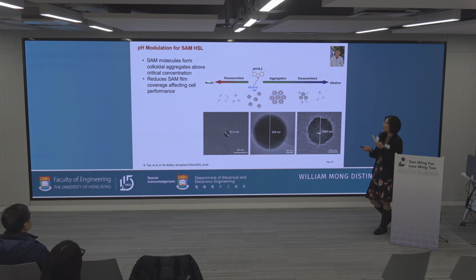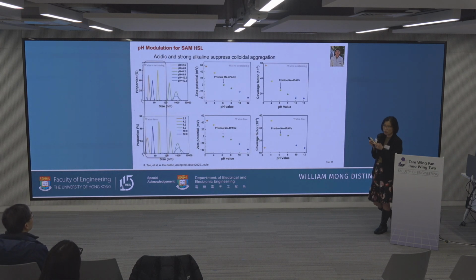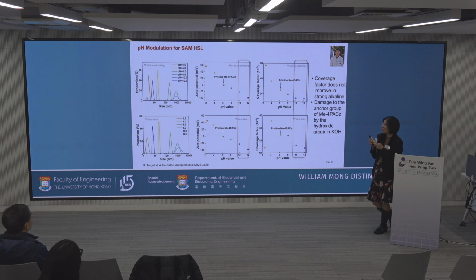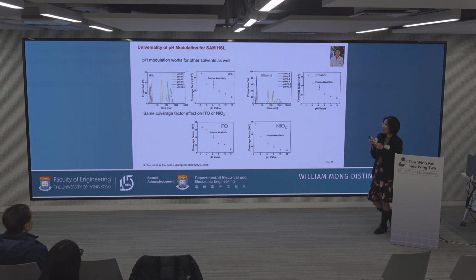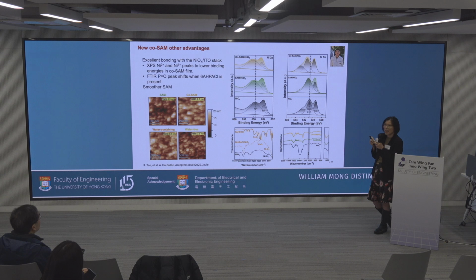So never mind, this one is about the SAM layer where we engineered the pH of the precursor solution, and therefore we are able to stop the molecules from aggregating. And when you do that, you will get much better coverage. We're able to do that by changing the pH to very low pH or very high pH to stop that aggregation and get very good coverage. And also in this work, we're able to improve the stability of the tandem.